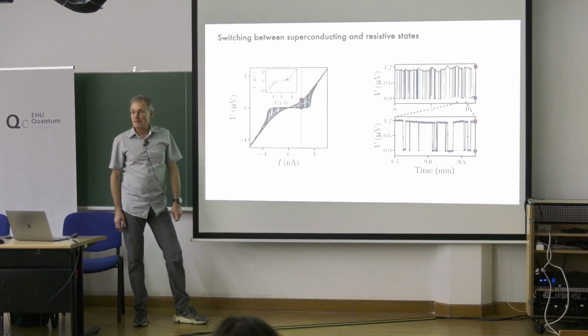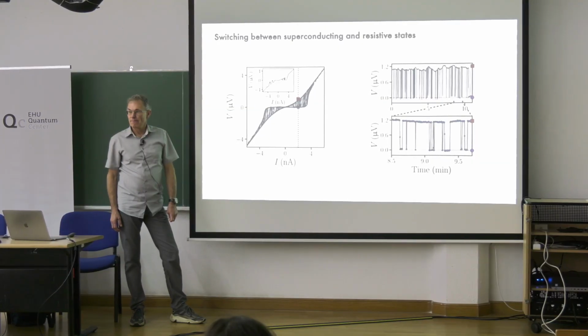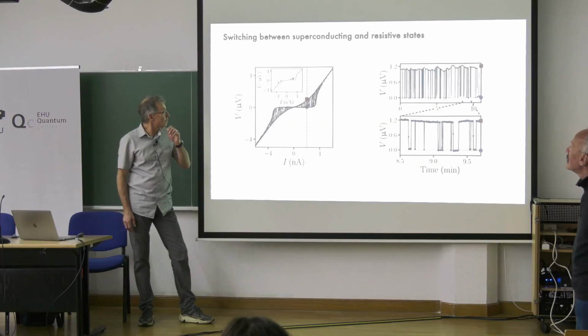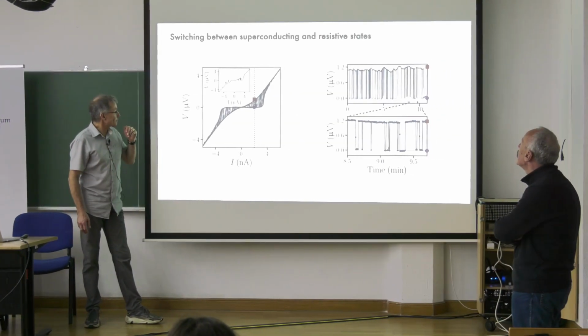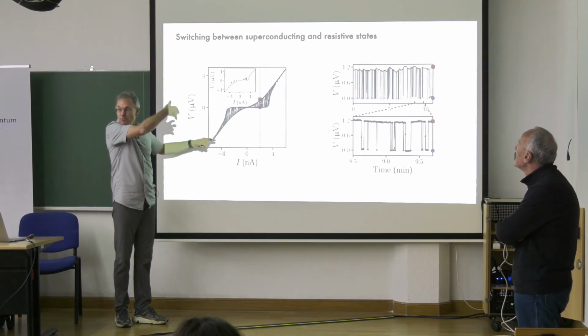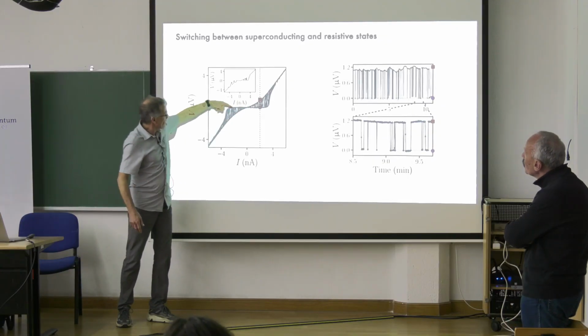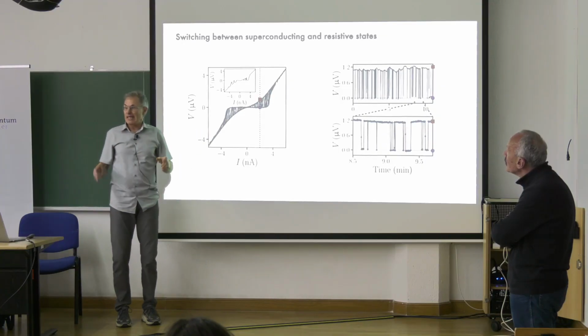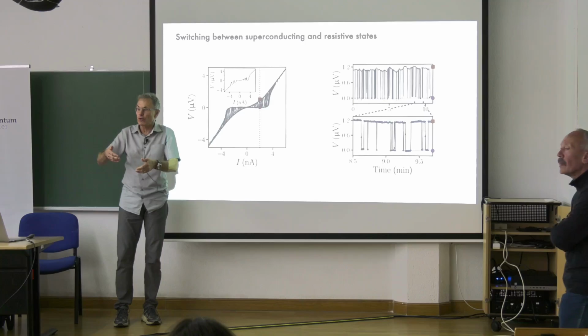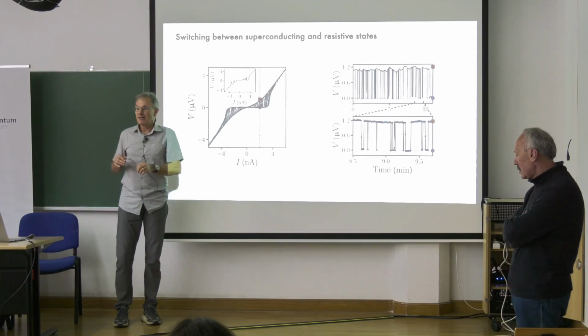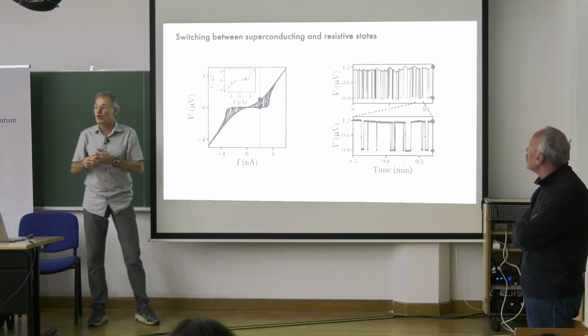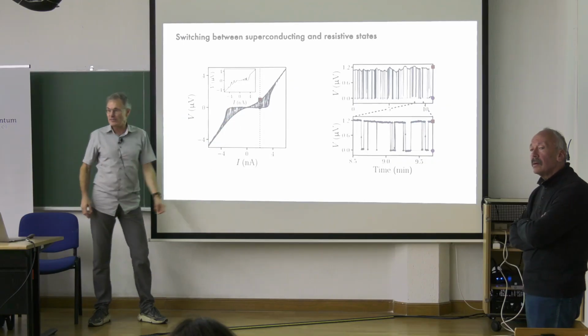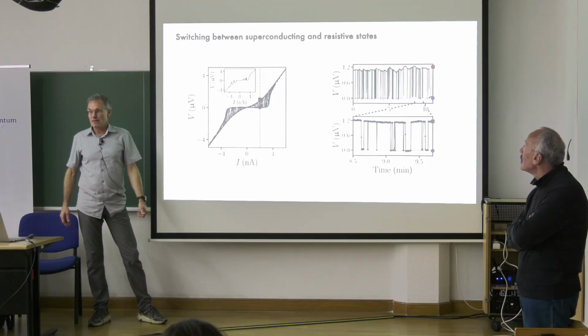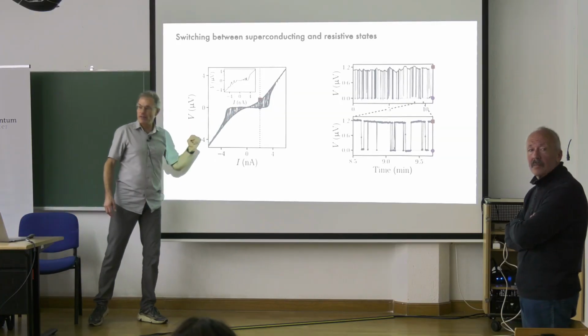So you have actually computed time evolutions, and that's what you are graphing there. So it's time dependent, if I understood correctly, which is why you have the time dependence on the right. Well, I think what is in this blue is more or less the superconducting state. When you do it many times and you plot, that's why it's this blue-white color. There is some noise in colors because sometimes you find this, sometimes you find that. And obviously the hysteresis depends on the applied B field. Yes, this curve depends on applied field.